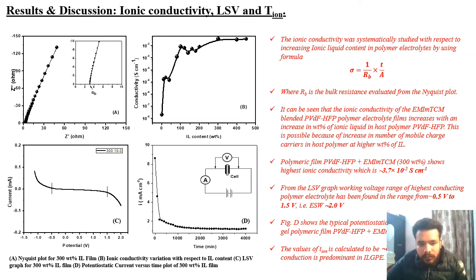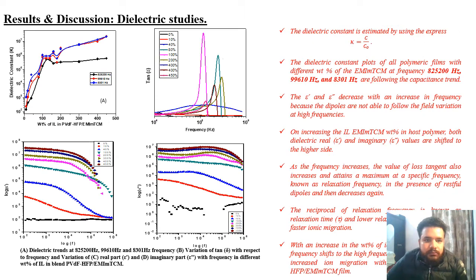And from the TION graph, which is present on the right of it, we have done a current versus time graph, the potentiostatic studies. They are showing that the ionic current is the major source of current inside the films. So from here we have calculated the TION, and we got a value of 0.93. So we can see that 93% of the charge carriers are ions inside the films.